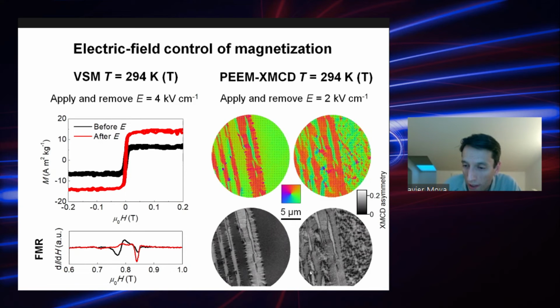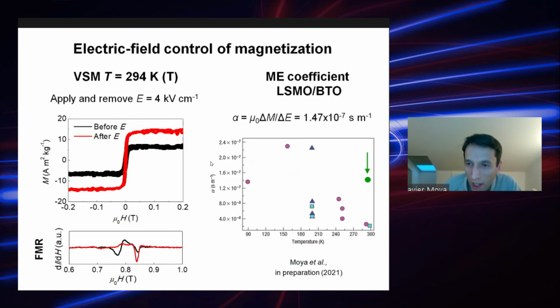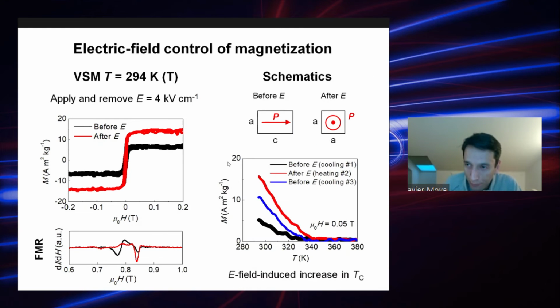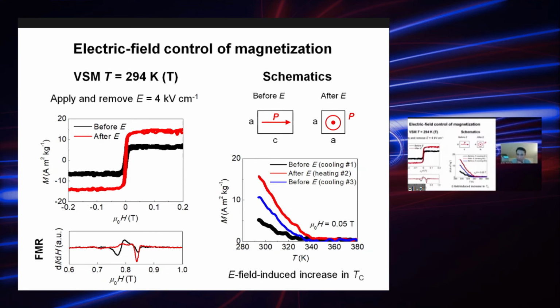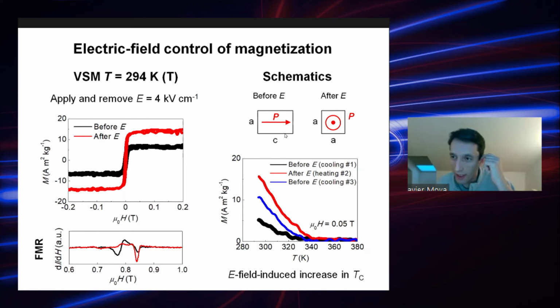And then when you apply an electric field to the substrate, you see you convert these low magnetization regions into high magnetization regions. So this is why this peak disappears and this peak increases, and then the overall magnetization is increasing. Now, the explanation for this effect again lies with the strain coming from the substrate. So if you remember, these substrates initially in the tetragonal phase have mostly the polarization in plane, and then you have this kind of structure of polarization pointing to the right and then down, to the right, down. So you have this kind of pattern.